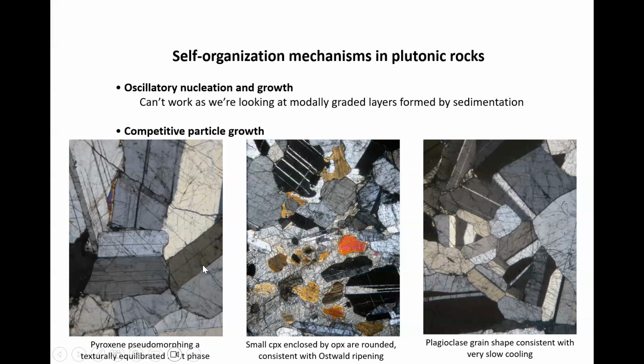The other thing that you can see is that in some of these plagioclase-rich regions, the grain boundaries aren't nice and smoothly curved. You can get them really irregular like this, but the irregularities are pinned by thin films of pyroxene. So we've got pinning during grain growth, which again needs slow cooling in the subsolidus. But what's interesting is that we commonly see these little cusps of clinopyroxene on the plagioclase grain boundaries, and I'm pretty sure that they're pseudomorphing a texturally equilibrated melt-filled porosity, which again says really slow cooling.